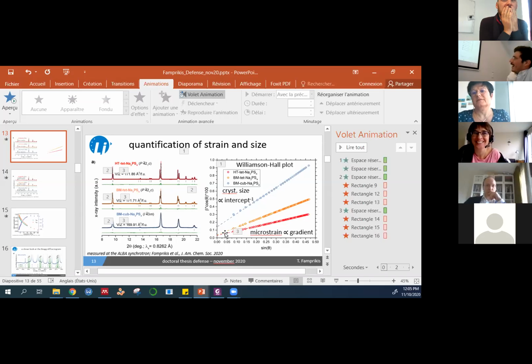Sorry to interrupt. In fact, theoretically, you are supposed to use the calculated line, but calculated separately, more or less line by line, because in order to be able to distinguish between possible strain or size effects depending on the family of crystallographic planes. Here, if you consider the calculated line, it could be hidden, more or less.